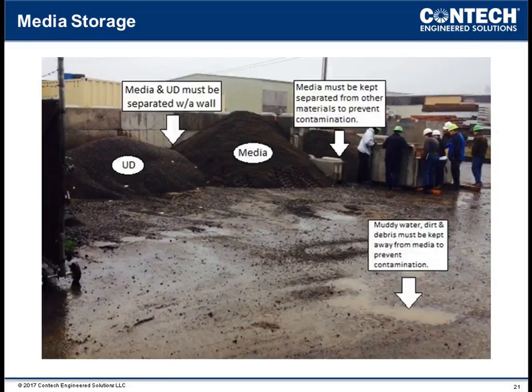There should be separation between bioretention media and any other media. Here you see the underdrain and media are stored next to each other, and the media is actually overflowing into other material on the other side. In addition, tainted water and debris should be kept away from the media to prevent contamination, and silt socks are recommended for use where this is an issue.